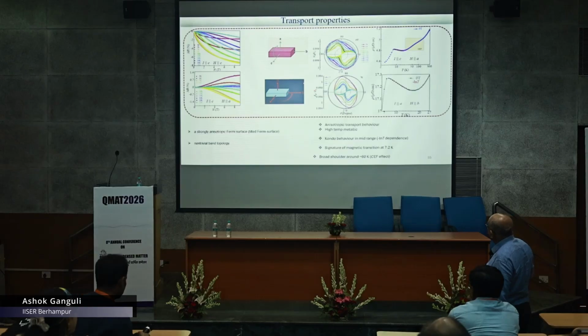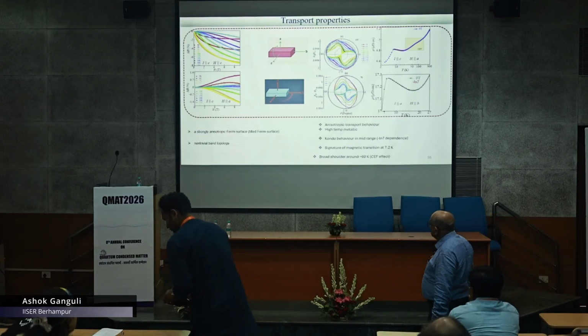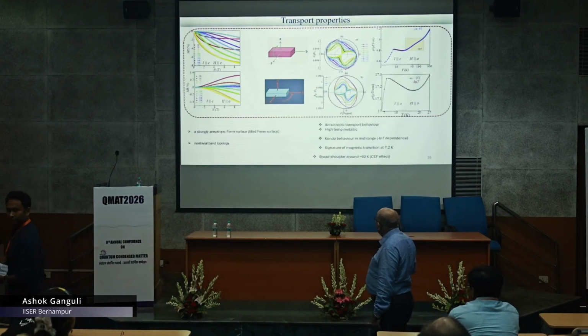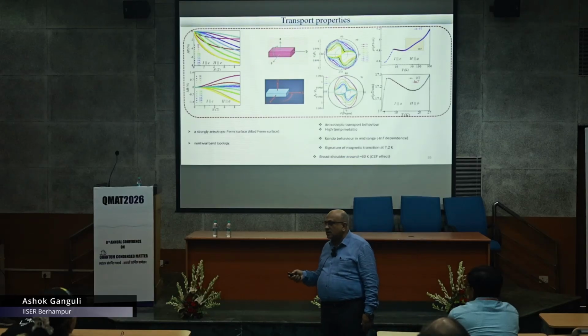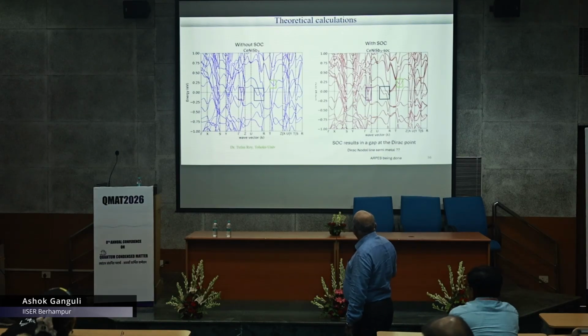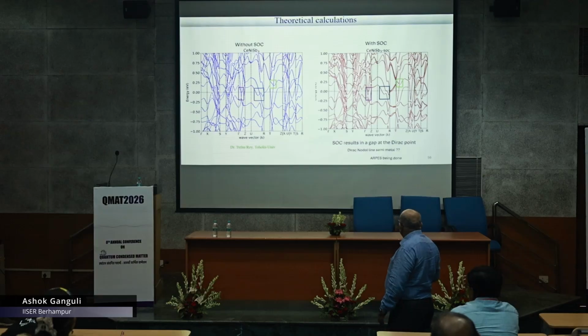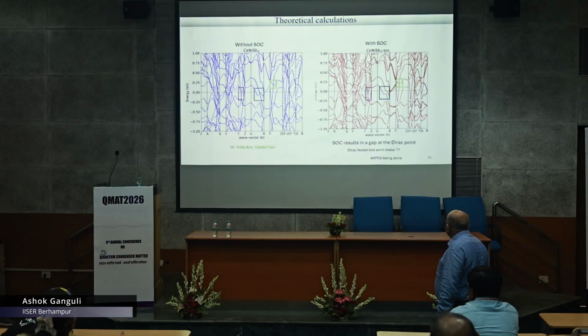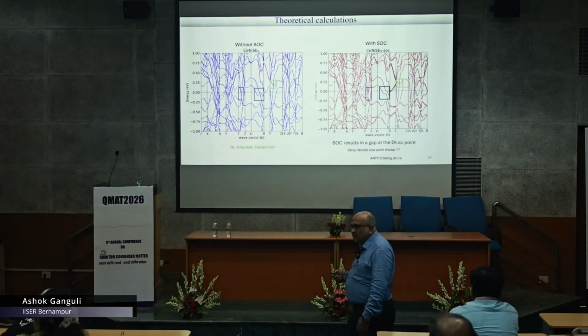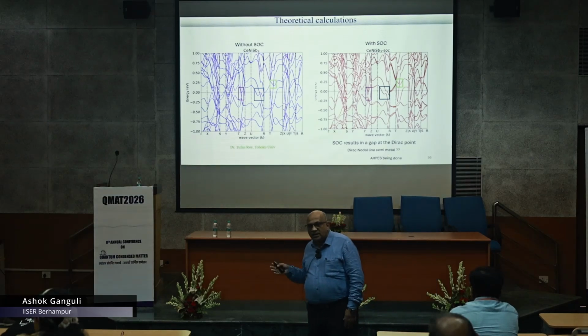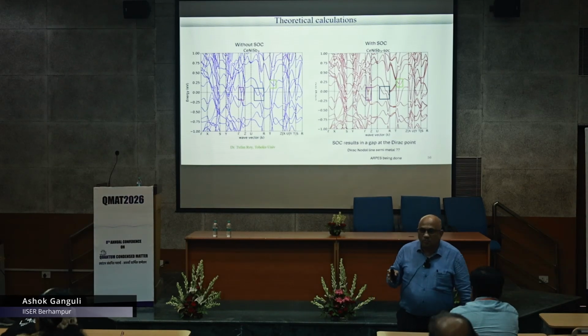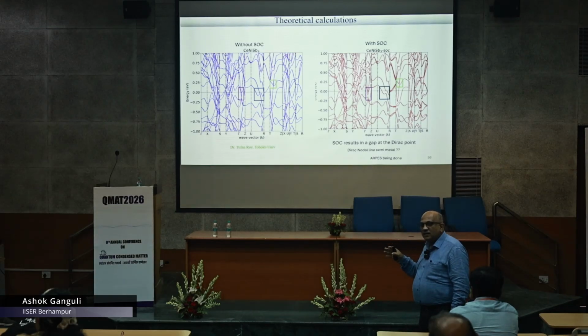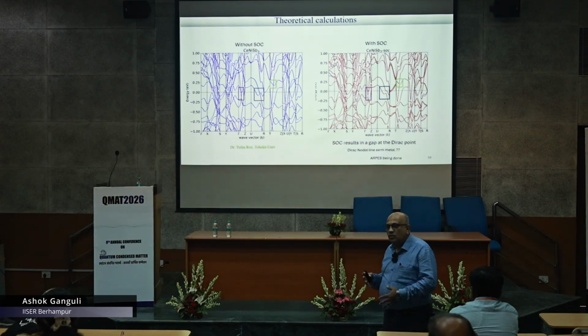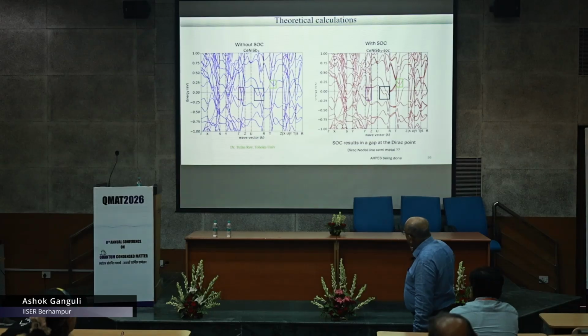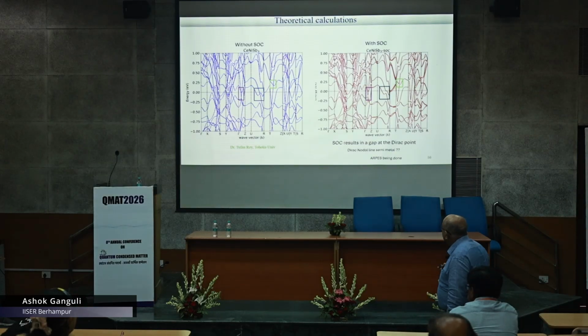As you see, it's a highly anisotropic shape, and it's also tilted, which gives you a signature of a non-trivial behavior. So we have got these spin orbit coupling gaps at the Dirac point. This appears to be a Dirac nodal line semi-metal, but currently ARPES work is being done. But from the data that we have, we are saying Dirac, but we are also thinking in our mind it is going more towards a Weyl semi-metal. And that will be proved when we get the ARPES result. So I will stop here.